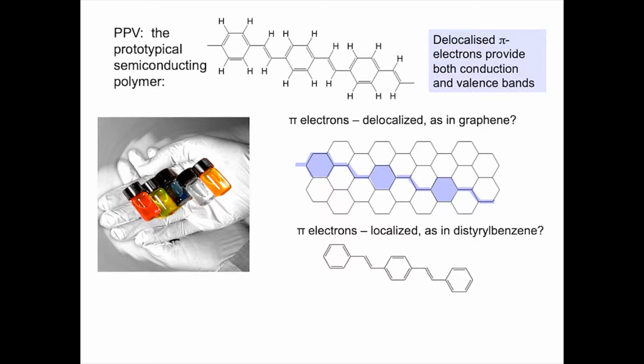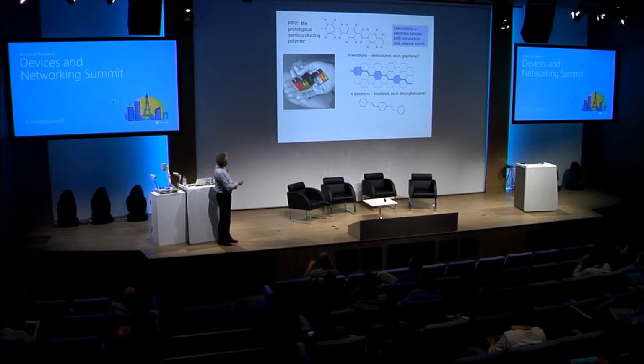Well, to wander a little bit into the science, there are very different views of how to describe these molecules or polymers, depending on whether you come from a physics background or a chemistry background. If you're a physicist, you would say, well, graphene is not very different from silicon, and electrons are actually completely free, so that if you absorb a photon, you produce an electron and hole, and they'd wander away from one another, just like silicon. But if you came from the chemistry community who've looked at functional molecules, electronically functional molecules, for an equally long time, you would say, well, the excitation is actually naturally confined. It's quite small, because there are strong electrostatic interactions that keep electrons and holes together.